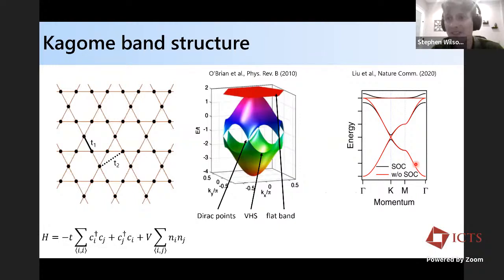Okay, great. So this is a Kagome conference, so I'm not going to belabor the background so much, but maybe for the students, just to remind everybody, one of the primary motivations of looking at electronic states in Kagome metals is that as a generic single orbital tight binding model, you get this interesting coexistence of features in the band structure comprised of, for instance, a hopping interference-driven flat band, of which many people are trying to develop systems where the Fermi level is within this flat band with the kind of interesting states predicted to form there. And then you also have Dirac crossings at the K points in the Brillouin zone, as well as a pair of saddle points that give rise to Van Hove singularities at the M points in the Brillouin zone.